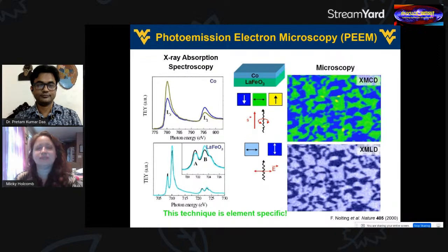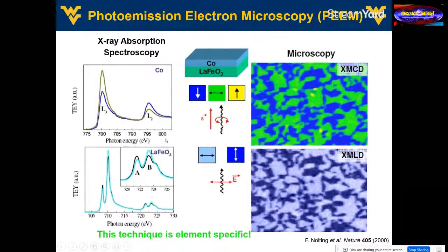but we're following a similar idea. So here on the top, we have a cobalt magnetic system. So you see these cobalt domains that I had in the last slide. And then if you shine in with light that is specific to the cobalt edge, you can look at the cobalt domains. If you adjust your energy to a different element, like in this system, it's lanthanum ferrite.